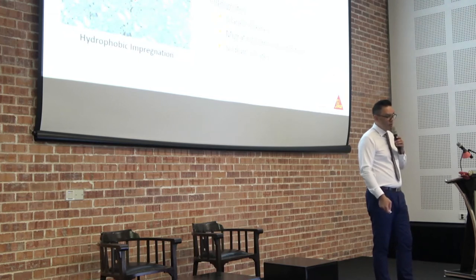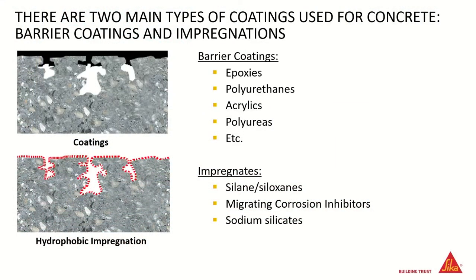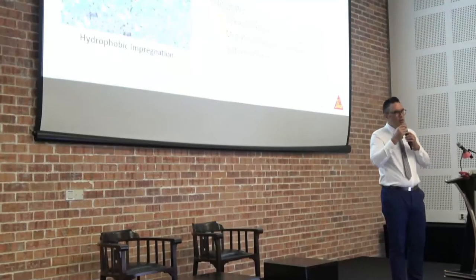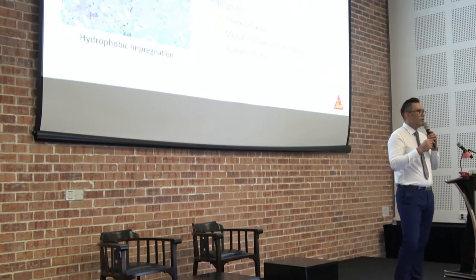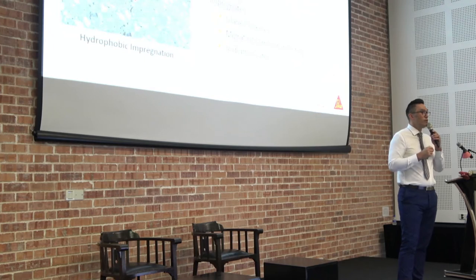On the other hand, the impregnates don't allow a water molecule in, and a water molecule, if it penetrates in, will usually carry with it some chlorides, or sulfates, or other dissolved aggressive solution. So if we can keep that solution out in the first place, there's less damage it can do on the inside. The other benefit is that you still have a breathable surface. As the concrete dries out, that vapor comes out of the concrete quite easily, even though it won't let any more in. The drier the environment inside, or the lower the humidity inside your concrete, the less damaging it is to your reinforcement.